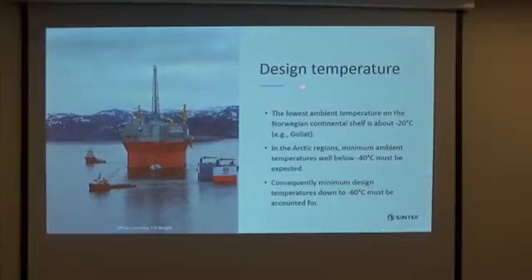Here's the temperature. This is the lowest ambient temperature on the Norwegian continental shelf at the moment. It's something like minus 20 degrees, and this picture shows a newly operated oil platform called Goliath. In this area the temperature is minus 20, but we have to expect in Arctic regions a minimum ambient temperature well below minus 40. Consequently, minimum design temperature of materials can be down to minus 60. So this is also what our project is aiming for. We test most of the materials at minus 60 degrees or even minus 90 degrees.